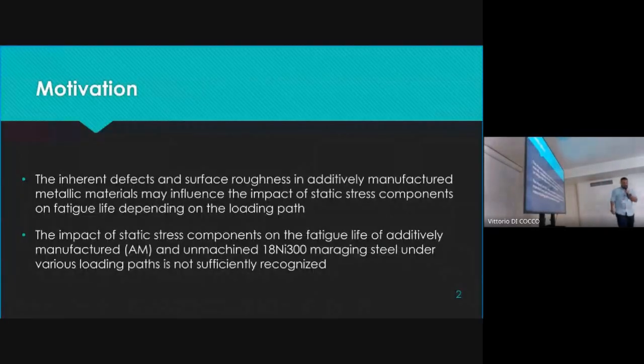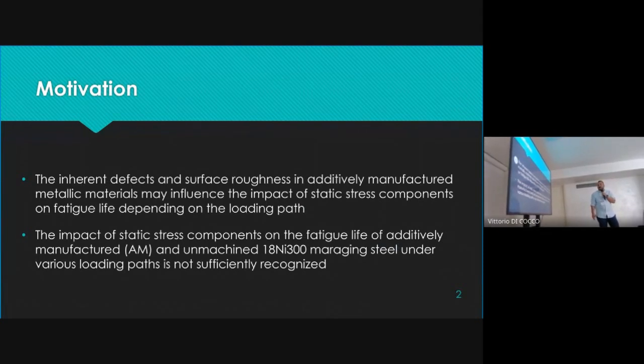So our motivation was that the inherent defects that additively manufactured parts have, like defects on the surface, roughness, and porosity, might have a different impact on mean stresses than the standard materials. Also, the static stress component's impact on the fatigue life in additively manufactured maraging steel 300 is not well and sufficiently recognized in the literature.